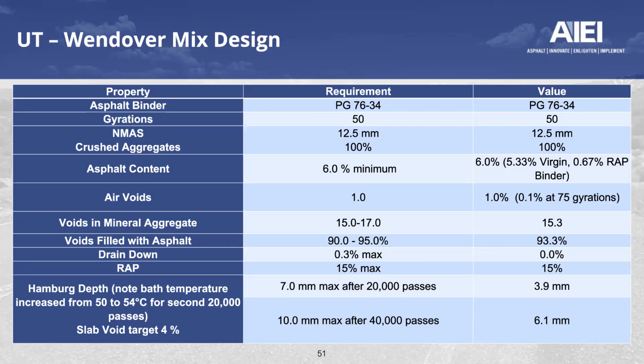What's also noteworthy is that next line, the RAP. Historically, in the state of Utah, they have not allowed any RAP in their surface mixtures. This was the first mix that they did allow RAP, at 15% by mass. That equates to about 12.5% binder replacement. It's also noteworthy, and it's not seen here, that they do not allow any natural sands, any natural material. It's 100% crushed material coming out of the quarries in the Wasatch Valley primarily. So 15% RAP is allowed, but no sand.